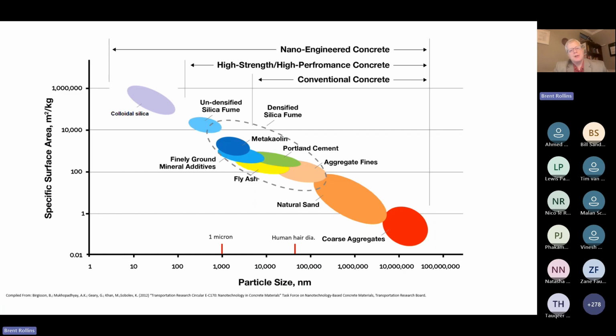That small size translates to surface area. You can see across the bottom of this graph, the x-axis is a log scale, and it is in nanometers. A coarse aggregate here, about a 20 millimeter coarse aggregate, is going to be in the neighborhood of 10 million nanometers, so up to 20 million, somewhere in that neighborhood. And then as it gets smaller and smaller, you can see that the surface area on the y-axis goes up. Most conventional concrete deals with these materials here.